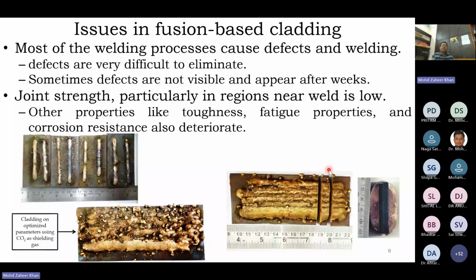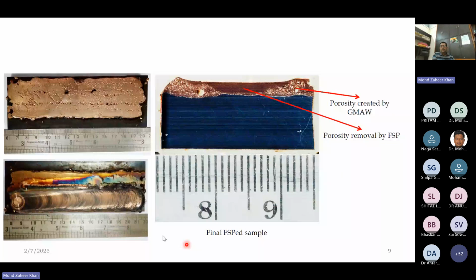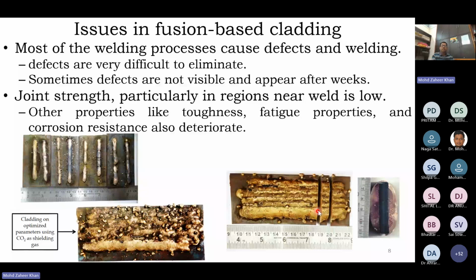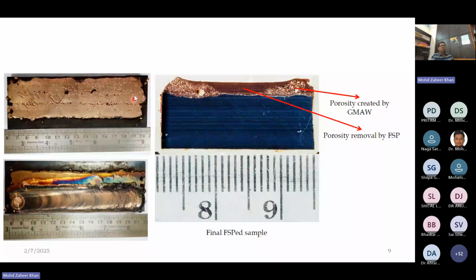As you can see in this photograph, we thought of why not incorporate our friction stir welding process to improve upon these problems caused by the gas metal arc welding process. So this plate was prepared, where a layer of copper was deposited on mild steel, and then the top surface was milled down to some extent so that the surface became flat. If there were no porosity, then after milling, this copper cladded plate would be ready for any application. But as you can see over here, there are a lot of porosities which were further exposed when the surface was made plain.